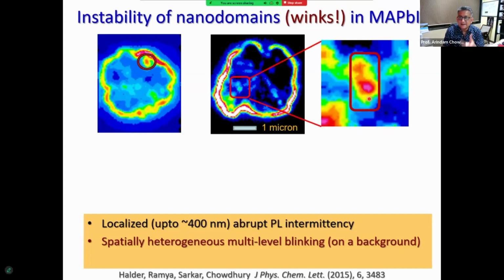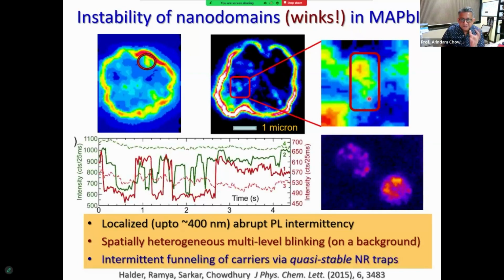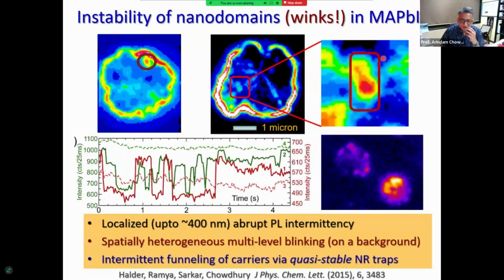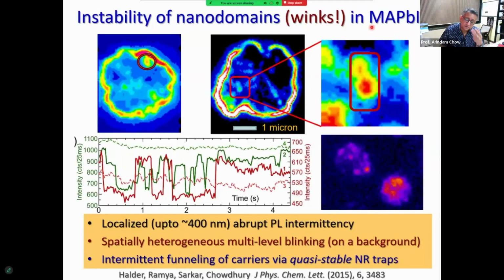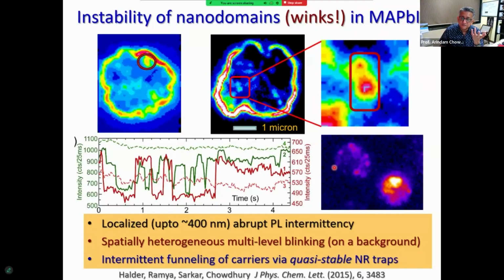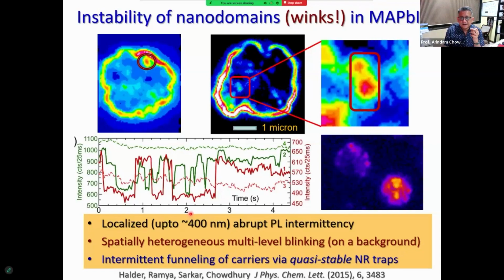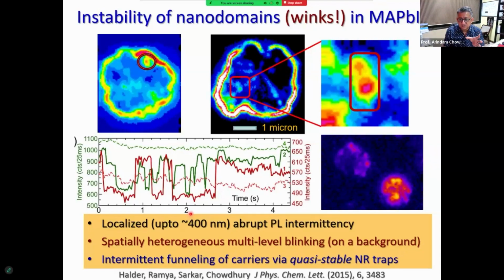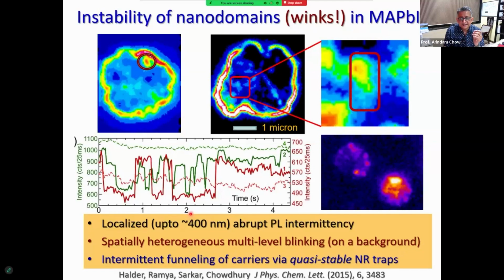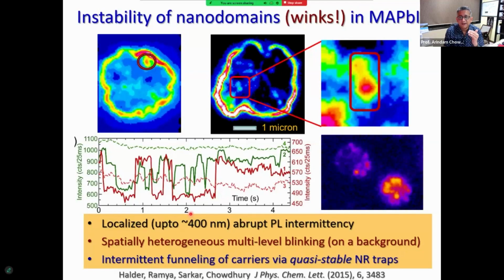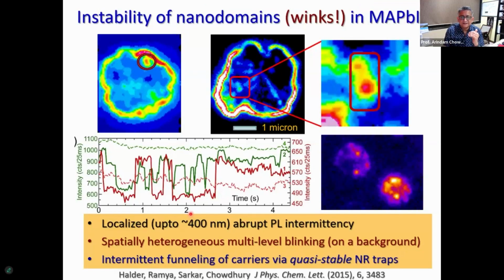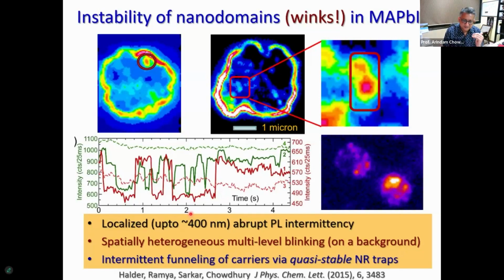It's basically winking and is coming back. And this behavior was not only there for the doped system, where we doped it with thiocyanate, but also for the MAPbI3 as well. We would see these fluctuations. And the difference between what I told you earlier and now is that here, every fluctuation that we observe is happening on top of a background level. And here you also see some sort of a multi-level jumps between states, all right?